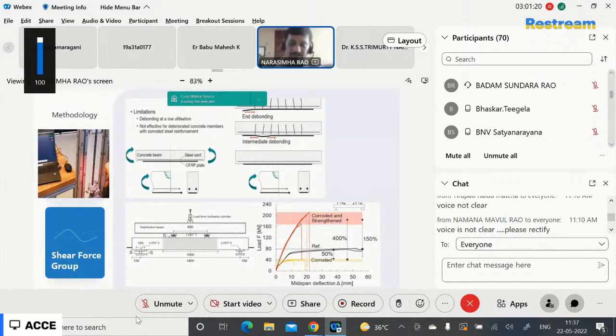Once we take the uncorroded control specimen, we compare it with the yellow one. Once there is a 50% degradation in the steel area, there is a drastic decrease of 50% in the load carrying capacity. Here we are measuring the load deflection curves. The load is applied at the midspan in a 2-point loading, similar to a flexural loading under the 2-point test. The midspan deflections are measured with LVDT equipment. Once we measure the load deflection response, there is a drastic 50% reduction in the load when there is approximately 50% degradation of the area of the steel.